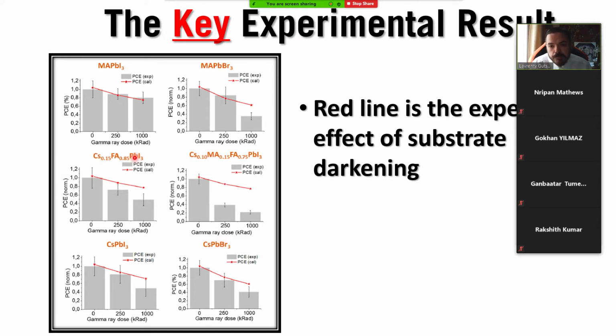The other hybrid materials degrade relatively quickly. But methylammonium lead iodide, in fact, did not degrade at all, because the experiment was done under glass, and when glass is irradiated, it darkens. In space, the way they get around this is they use quartz, but here they used glass, and the glass darkens. So this red line is the expectation of how much the power conversion efficiency will decrease depending on the radiation dose. As you can see, this can be attributed almost completely to the glass darkening. So the material under the glass has not degraded at all. Meanwhile, the bromide-based material degrades a lot.